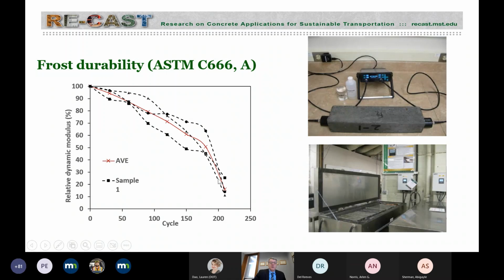We had a very severe drop of elastic modulus, indicating internal cracking of the concrete because of repetitive freeze thaw cycles. So you could say that the freeze thaw resistance of a concrete like this is poor. Normally you would expect to have at least 60% residual elastic modulus after 300 cycles. And even in certain Nordic countries, like Canada, for example, they specify 80%. So this concrete was not air entrained, but it's very tight, watertight, but did not really withstand this accelerated freeze thaw testing.